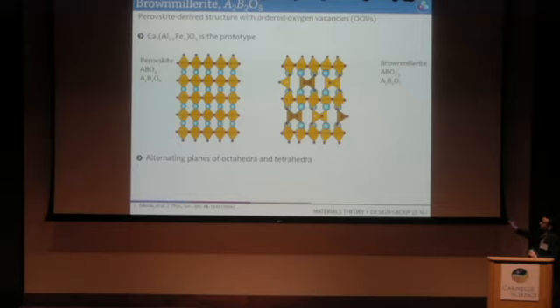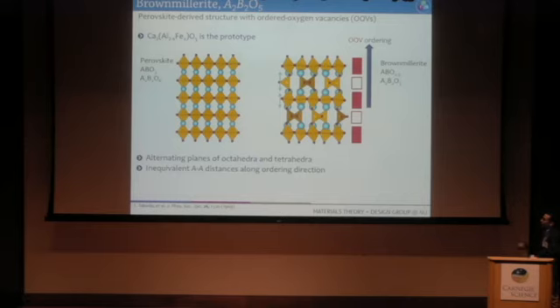If you write the chemical formula relative to perovskite, you see it is oxygen deficient, okay? So you have ordered anion vacancies in this structure. So you can see, in terms of the geometry I've shown you, you have oxygen vacancy order in this direction. So I have a plane of oxygen vacancies, fully oxygenated metals, and then another plane, alternating, in this chain-like structure. The other added feature in this structure, which you don't have in perovskite, is that you have different A-A distances spanning the different polyhedral units. So this A-A distance across from the tetrahedra is much longer than that across from the octahedra. So these A sites are much closer than these ones. In addition, you have displacements within these AO planes like that.